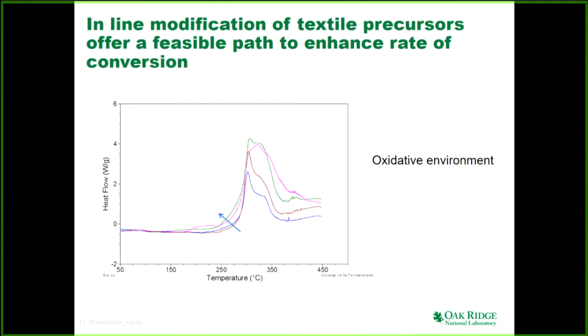And in this case, we can move it very fast, but that would create a problem for us later on, because before orienting the fiber during oxidation, it would start cross-linking, and that would create a crappy carbon fiber. So we don't want that. So we did a slight modification, and we tried to move the exothermic reaction towards lower temperature. So that's how. Now, is this heat affecting or air-based oxidation, cross-linking reaction?